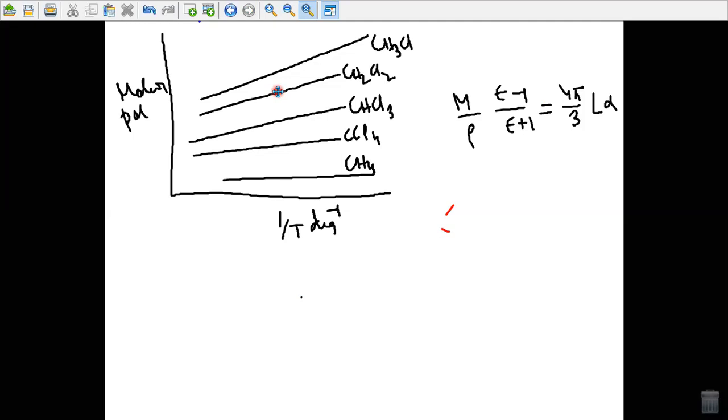In the absence of thermal agitation and the interactions among themselves, molecules with permanent dipole moments would all line up completely on application of an arbitrarily small electric field, so that the dielectric constant would be infinite from the Clausius-Mossotti equation. Actually the orienting tendency of the electric field is partly compensated by the thermal agitation, and in solids and some liquids, the orientation is hindered by close range mutual interactions of the molecules.